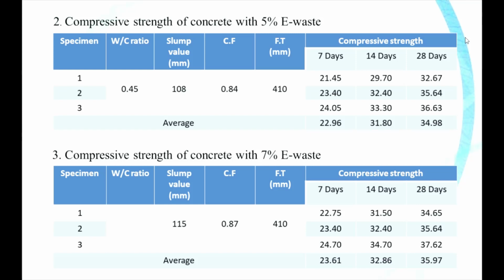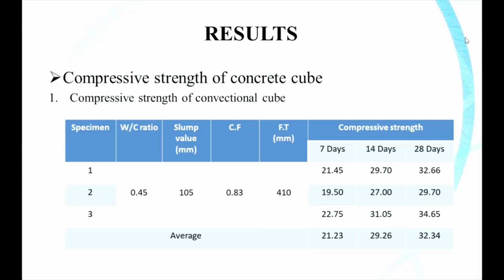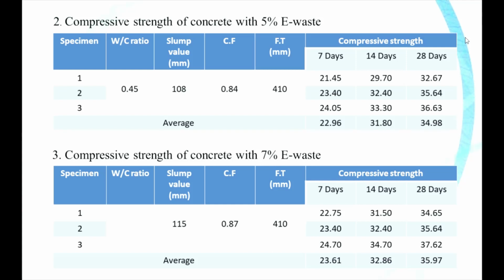The average strength at 7 days is 22.96 megapascal. At 14 days, 31.80 megapascal. At 28 days, there is a strength of 34.98 megapascal. As we compared it with the conventional cube, the first table, there is an increase in the strength with the addition of 5% of e-waste.